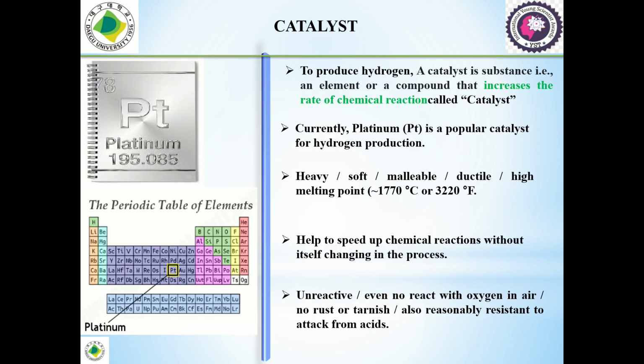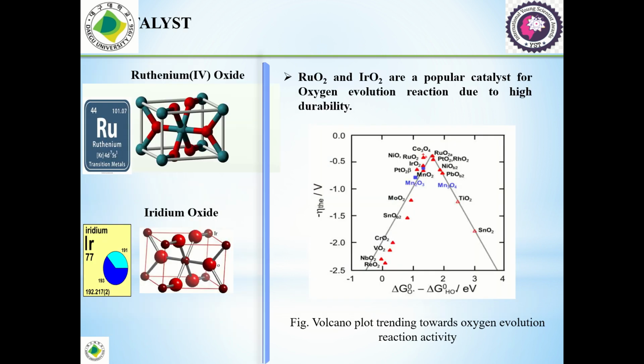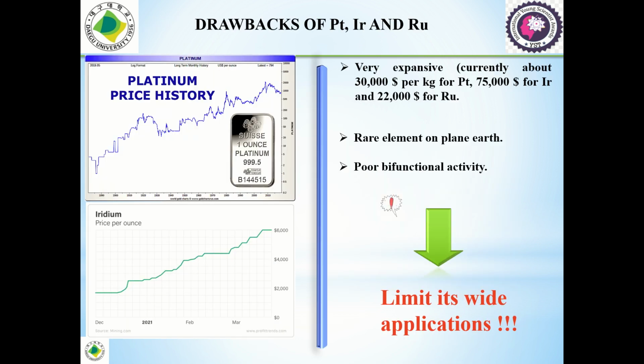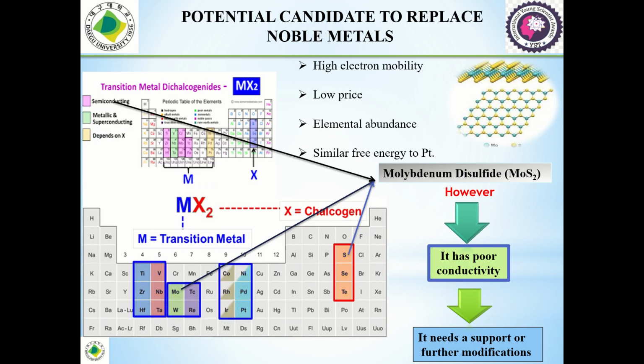So we need to use different types of catalysts, as I already mentioned: platinum, ruthenium, iridium. These types of materials have been used up to now to increase the reaction rate. However, they are very expensive and rare elements on planet Earth, and they have poor bifunctional activity, which limits their wide application. So to replace those materials, we chose MoS2. MoS2 has high electron mobility, very low price and elemental abundance, and hydrogen adsorption free energy similar to platinum. That's why we chose MoS2.